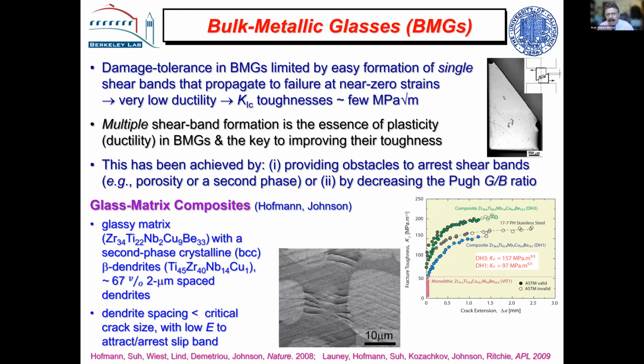Now, as you know, metallic glasses have this issue of forming shear bands, and a single shear band can basically reduce the ductility to near zero, and you get very, very low toughnesses and low ductility. But if you can generate multiple shear bands, the shear bands are in fact the form of plasticity. So if you get multiple shear bands and you can somehow arrest them before they cause complete failure, you can get good properties. And so this was first done by Bill Johnson and his student Doug Hofmann.